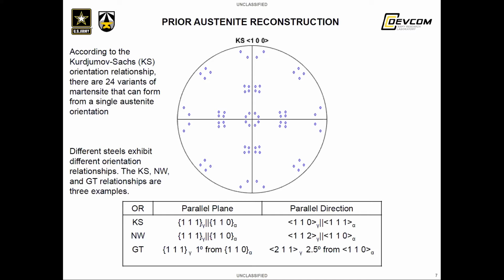So earlier I defined those as variants. There's 24 possible depending on which steel you're looking at. And those variants form with specific orientations that are typically possible. Those orientations are shown for a given orientation relationship called the Kurdjumov-Sachs orientation relationship in this pole figure here.